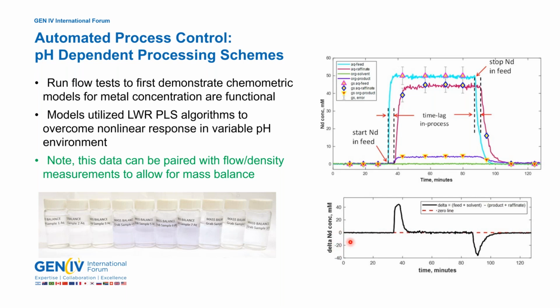So this is the plot we wanted to demonstrate mass balance. We look at the difference between what went into the contactor and what came out of the contactor. This is the delta neodymium concentration. What we're plotting here is a delta of what went in, that's the feed plus solvent, minus the concentration of neodymium in the organic product plus what was in the raffinate. At the very beginning, when no neodymium was in the system at all, it's 0. But right when we start neodymium into the feed, we see a delta. There's an offset here, and that's because we have neodymium in process.